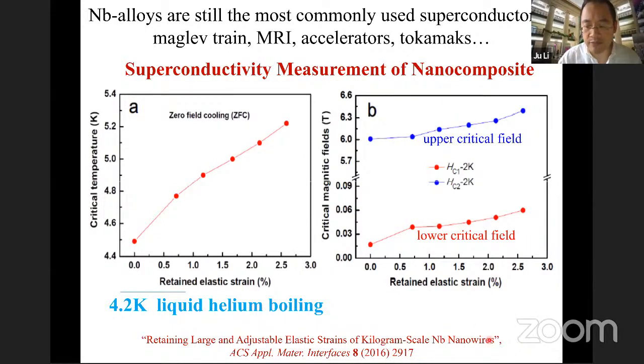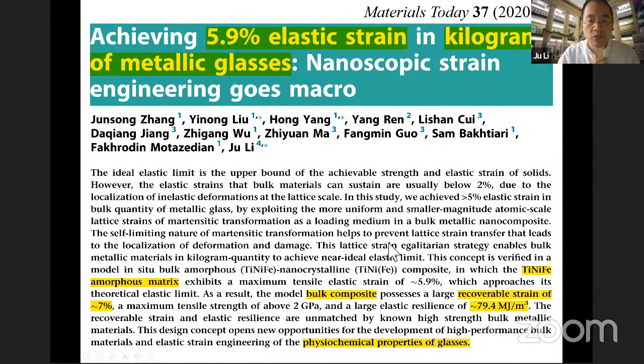So this is a demonstration of bulk scale, kilogram and kilometer long composite superconductor cables where you can do strain engineering. And more recently, there is another demonstration on this nickel titanium iron metallic glasses, where we are able to demonstrate kilograms of metallic glasses strained to about 6% elastic strain. And actually, metallic glass are used for the soft magnet cores of transformers. So this again, I think studying the magnetic properties of these materials is of interest.